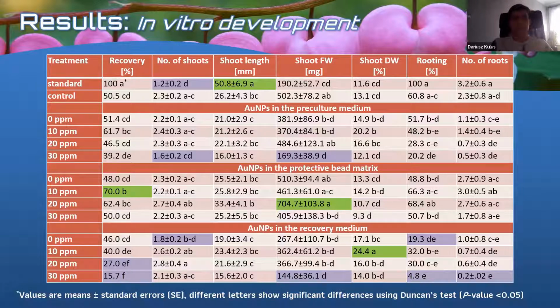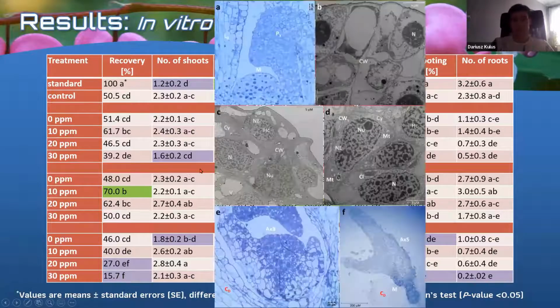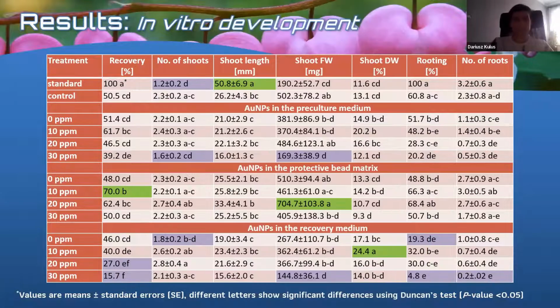Some other observations that we made demonstrated that plants after cryopreservation produced generally more multiple shoots in comparison to the non-cryopreserved standard. But this is quite a typical phenomenon, because as we observed in our earlier research, due to some cryo injury of the apical meristem, the axillary meristem can get activated, and that results in the production of some multiple axillary shoots. And here the nanoparticles did not affect this phenomenon. It was basically quite the same as in the control without the nanoparticles.